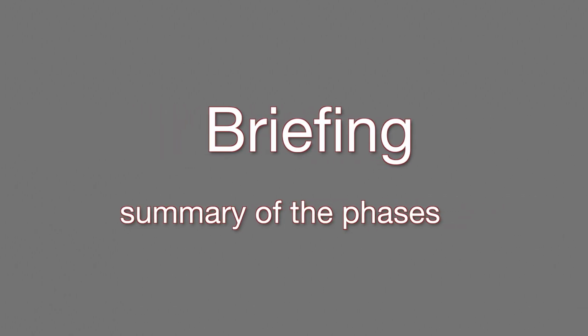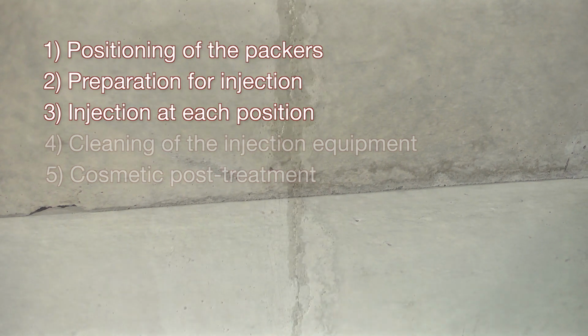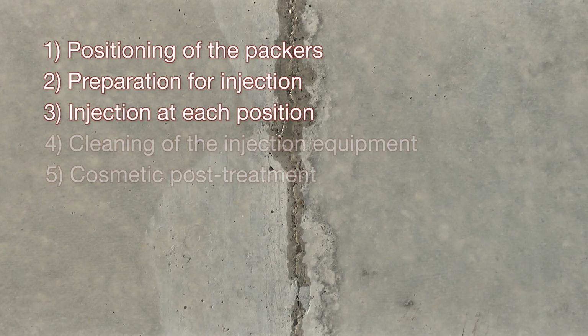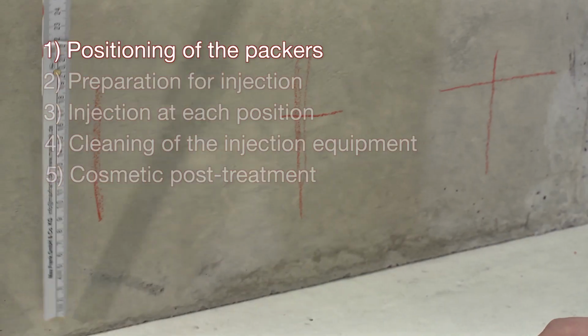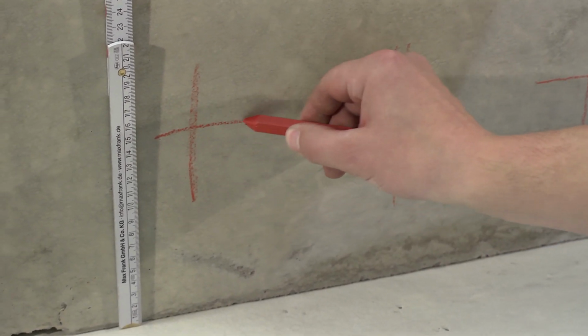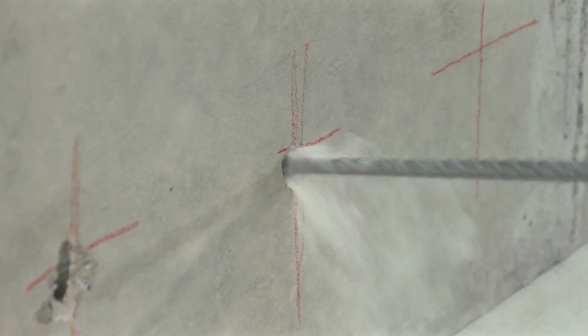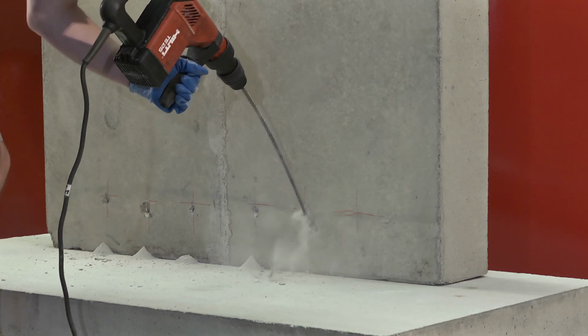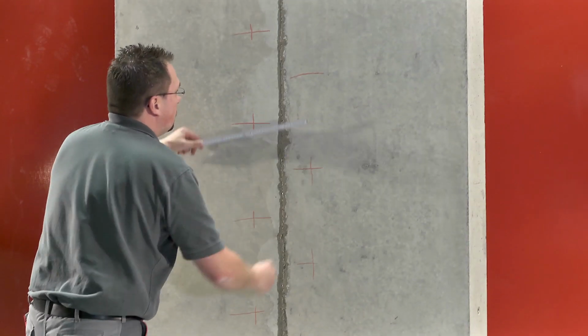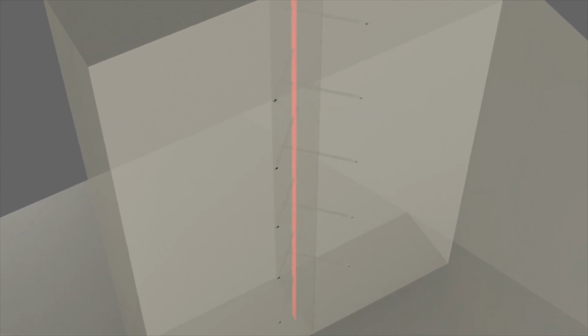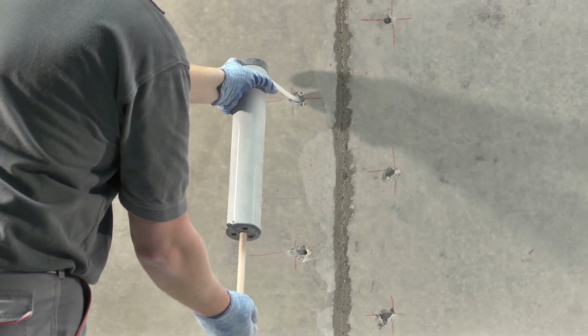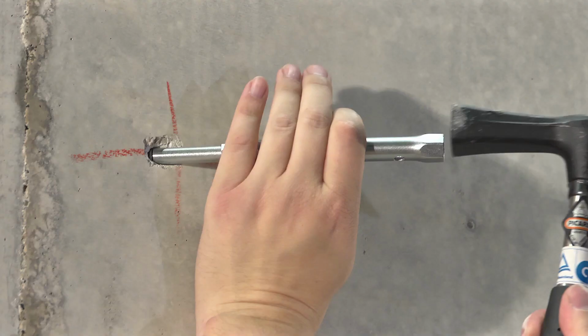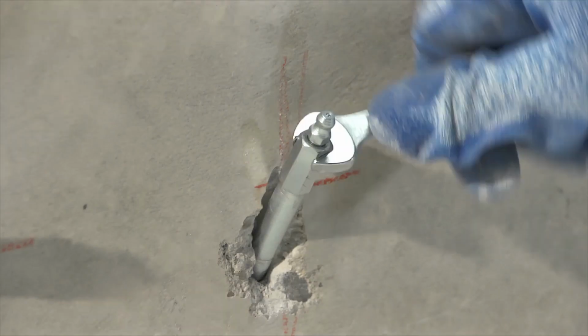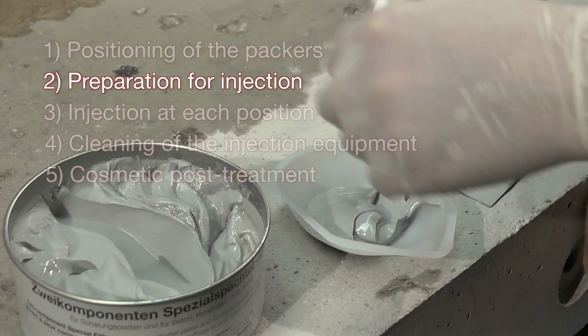Summary of the phases. For phases 1 to 3, the individual procedures will vary depending upon the crack or the joint. For phase 1, the drill holes must be drilled in accordance with the project requirements. If access is only possible from one side, the drill holes must be in single file. Otherwise, they should be alternated between the left and right sides. It is important that the drilled holes pass through the gap to be sealed at an angle of approximately 45 degrees at the cross-section center. Furthermore, the drilled holes must be completely free from dust and other debris. When inserting the packers, make sure that you do not damage their valve heads and check for firm seating.